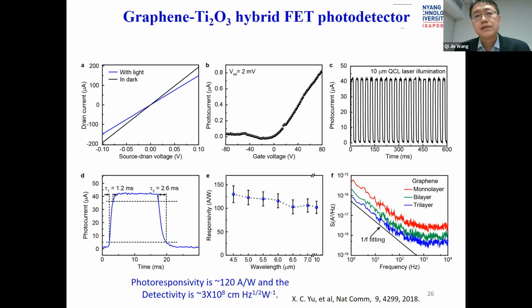Yes, so if you reach such a thin layer, traditional methods like those demonstrated in GST or even germanium structures still have some surface roughness variations. And then you cannot produce such an ultra uniform thin layer with 1 or 2 layers, or even 3 layers. Therefore, the 2D material naturally gives such uniformity over the whole period. Even now, with growth and fabrication technology improving, especially using CVD, such material quality also improves, which also allows us to fabricate large areas of such devices on 2D materials.